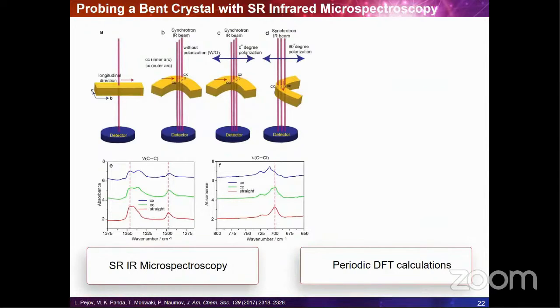Because the crystallinity of the bent crystal is lost as a result of accumulation of defects, we have demonstrated in this work that spatially resolved microfocus infrared spectroscopy using synchrotron radiation can be applied in conjunction with periodic density functional theory calculations to predict the spectral changes or to extract information on structural changes that occur as a consequence of bending.